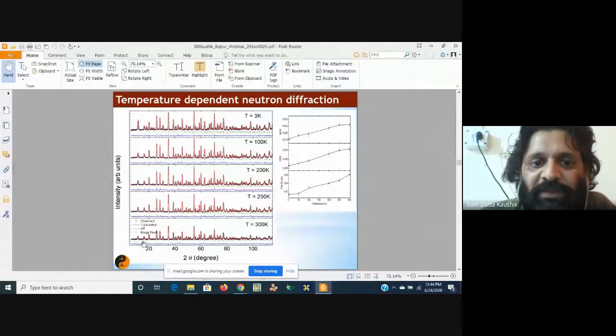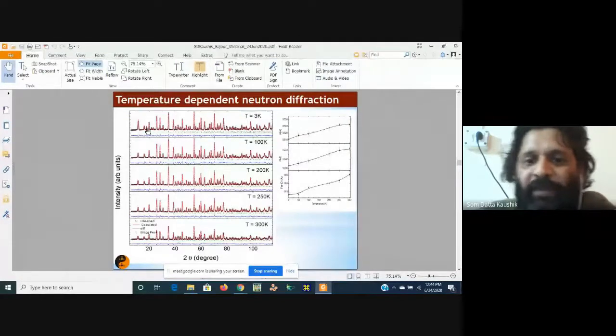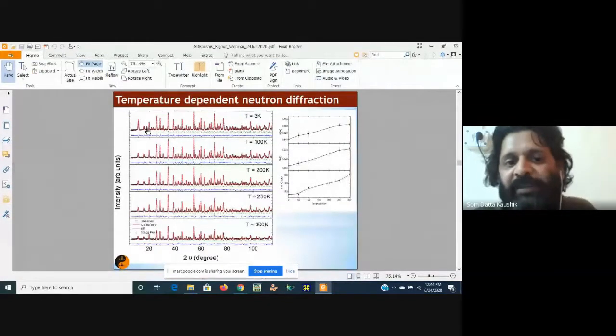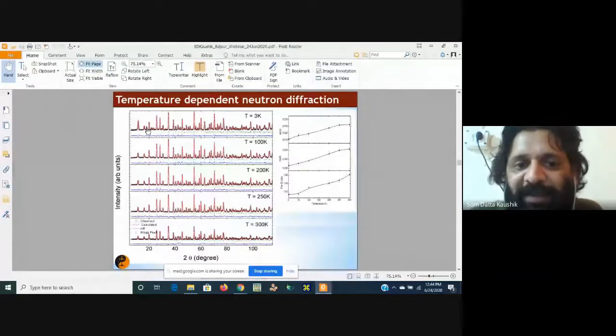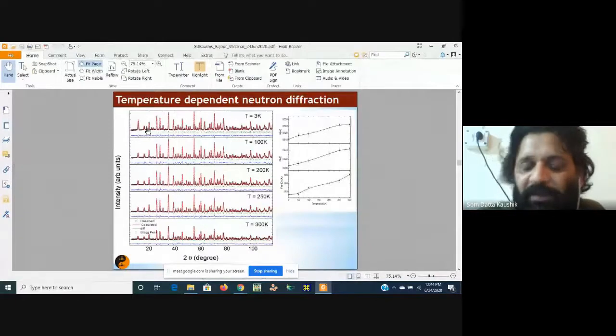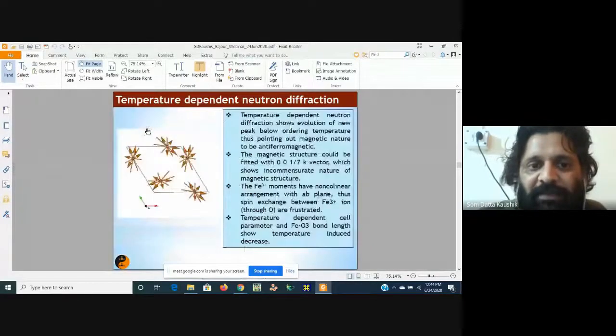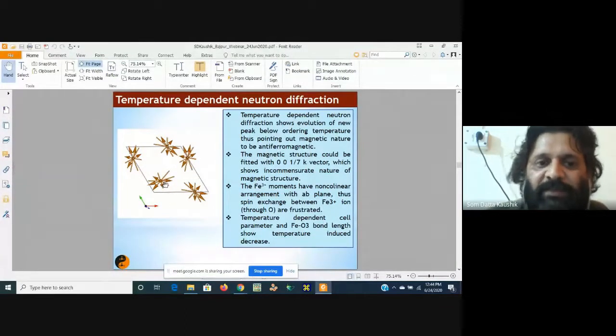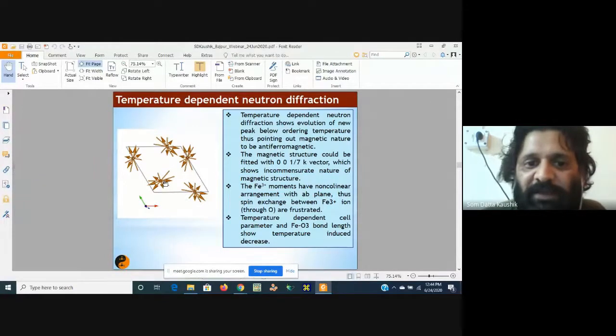At 300 Kelvin we have 3 peaks, but at 3 K one new peak is coming up. It is a clear signature of antiferromagnetic ordering, because of up and down spins you have cell doubling or cell tripling depending upon your sample. Because of that, you get a new peak. By analyzing this data, we can see what the spin structure looks like. I have shown it along the c-axis. This is basically a spiral kind of spin structure.